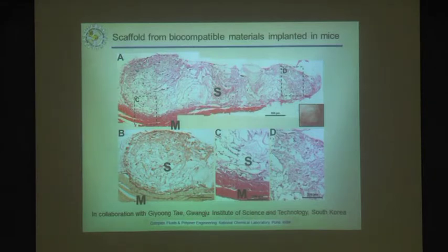One of the things that's nice about these materials, and I haven't spoken about that, is the fact that by changing the amount of cross-linker in there and therefore changing cross-link density, you can vary the modulus of these materials by about 2 orders of magnitude, probably more. We can certainly do 2 orders of magnitude in the lab.